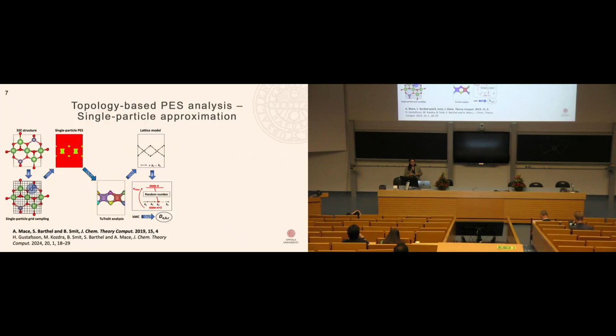So this is a challenge that I was working on during my postdoc period at EPFL, where I developed a cost-efficient and automated approach to map out a diffusion model for a mobile particle within any kind of crystalline structure without needing to know the topology beforehand. So the way it works is that we take our coordinates for our crystal unit cell, and then we take our lithium, and we sample on a regular equidistant grid the potential energy that the single lithium ion feels within this three-dimensional void space of our crystal material.